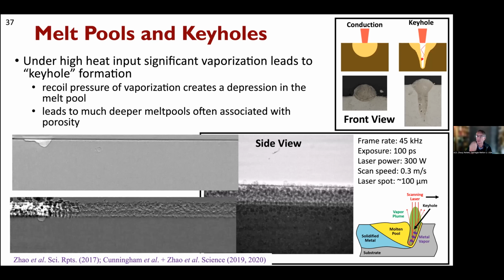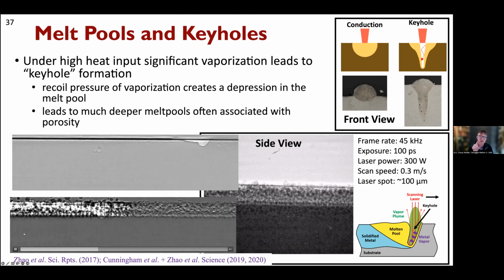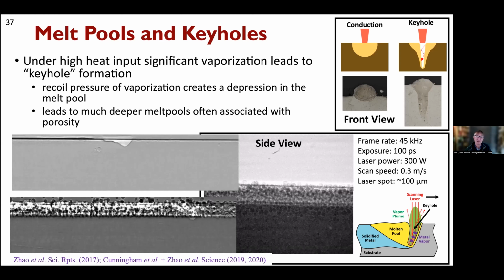So you get a plume. That's what's indicated in this little diagram. That vapor plume coming off through the reaction force pushes down on the liquid metal, displaces it. You get a keyhole, as the welders like to call it, and that has many consequences. So to show you what you see when it's clean, there's no powder, versus what you see when you have powder present, you get these characteristic vapor holes, and sometimes they're stable, sometimes they are not.